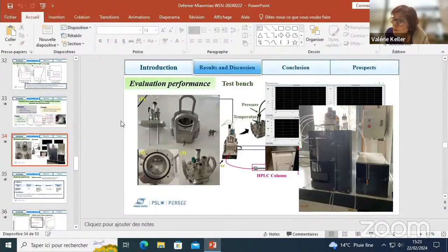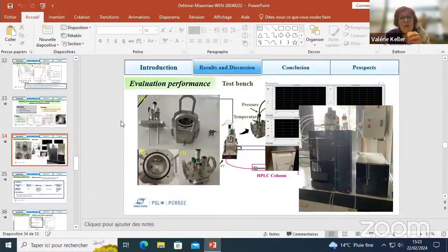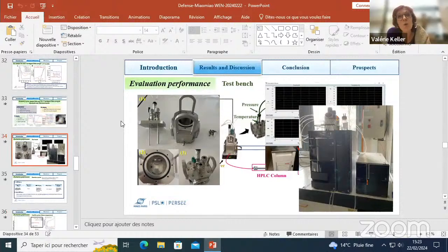Another point, it was interesting that you used two approaches for methanol formation, one using gas phase CO2 bubbling in the water solution, and the other one using sodium carbonate. I'm not sure, but did you perform the blank tests, I mean, without feeding any carbon-based compounds?